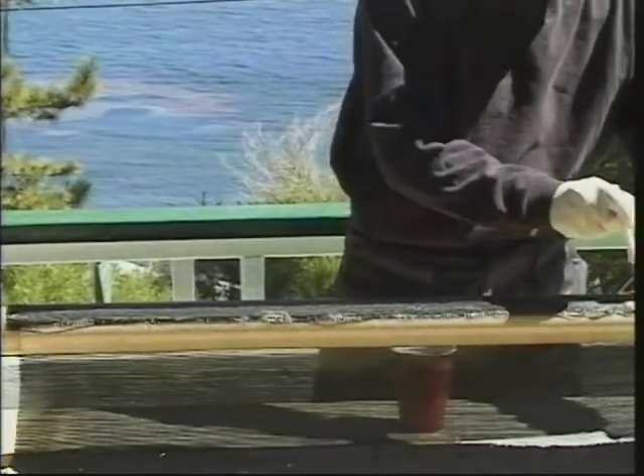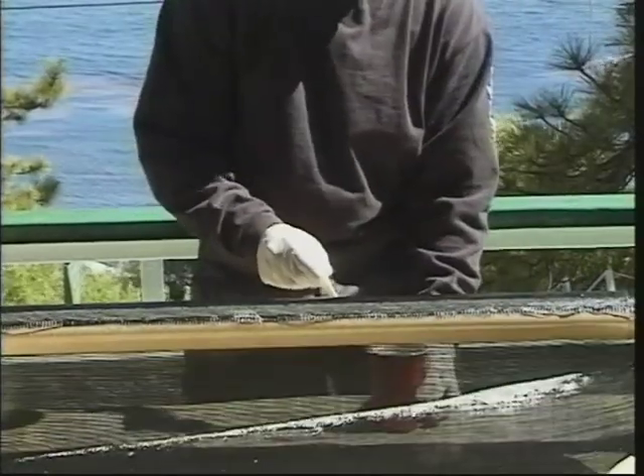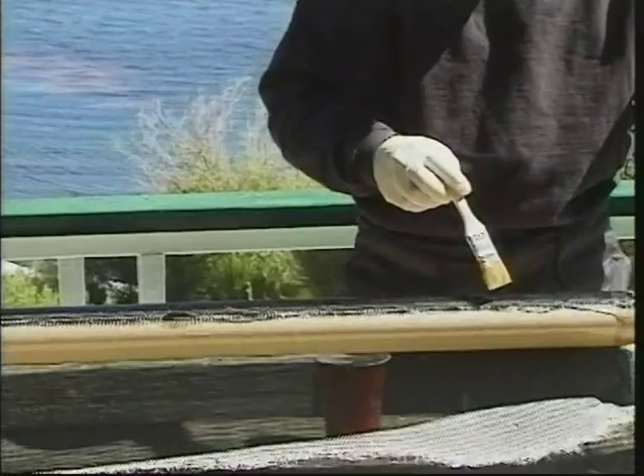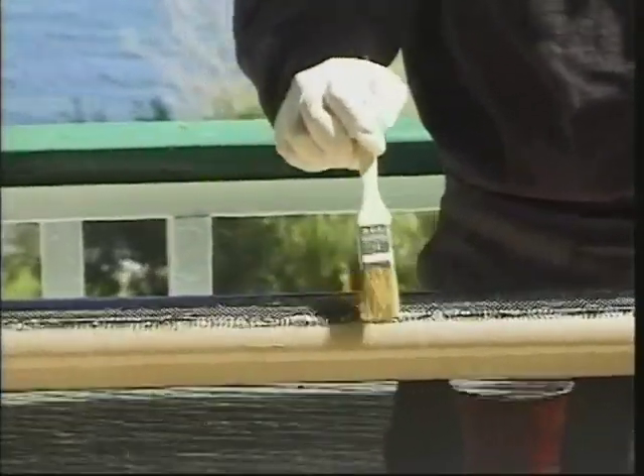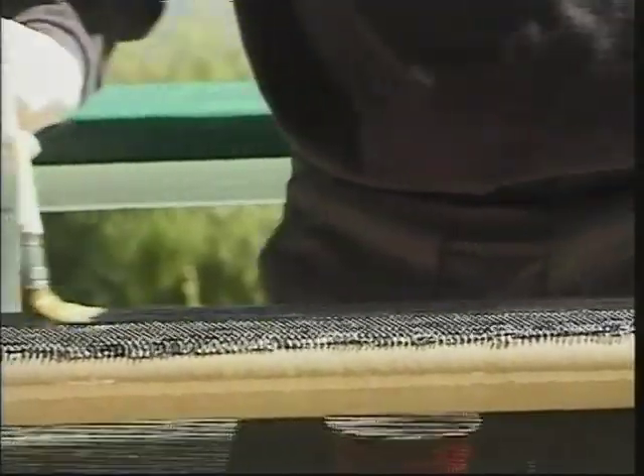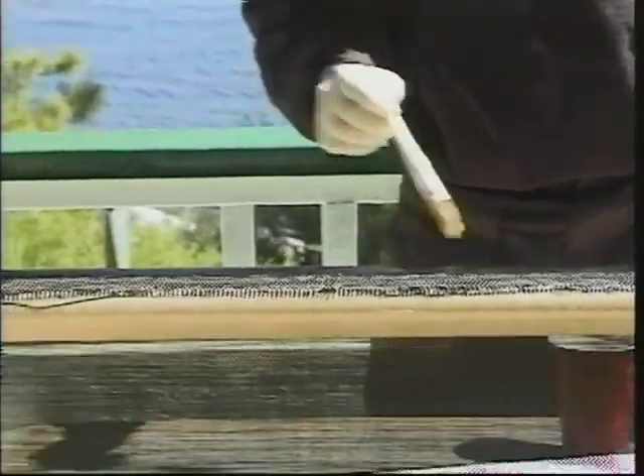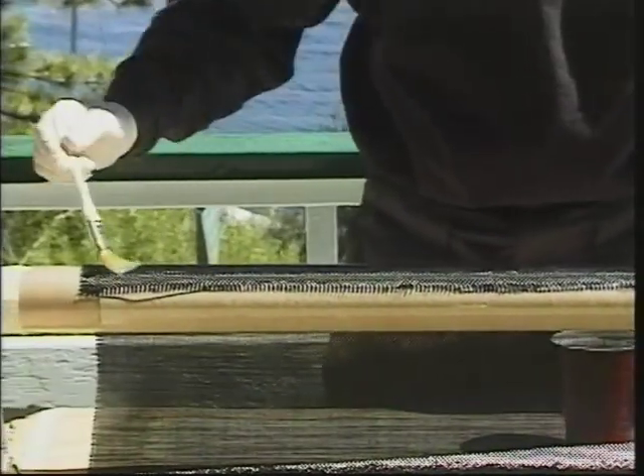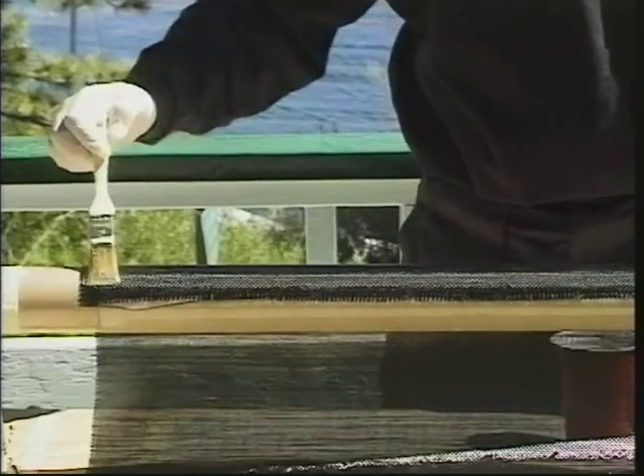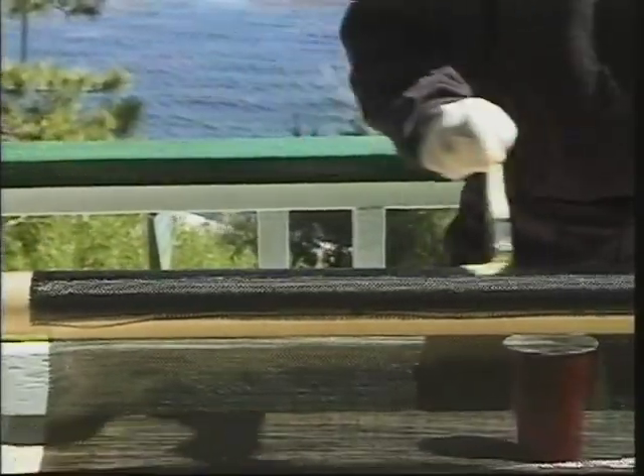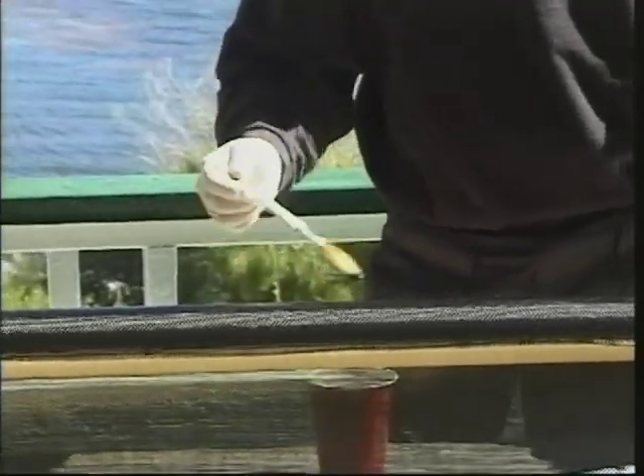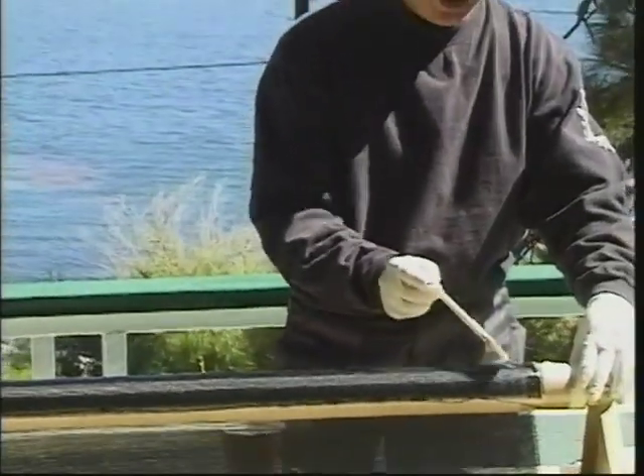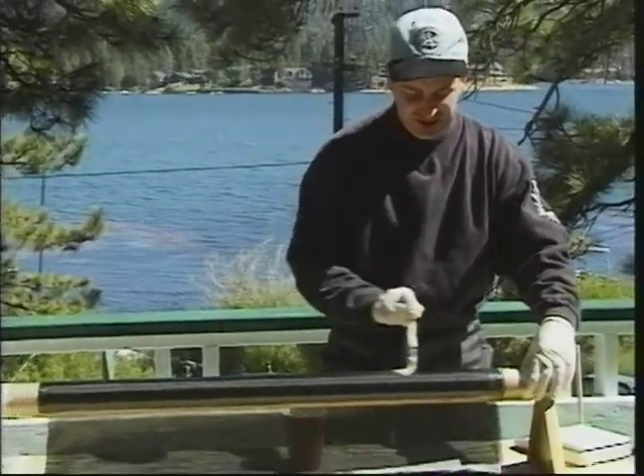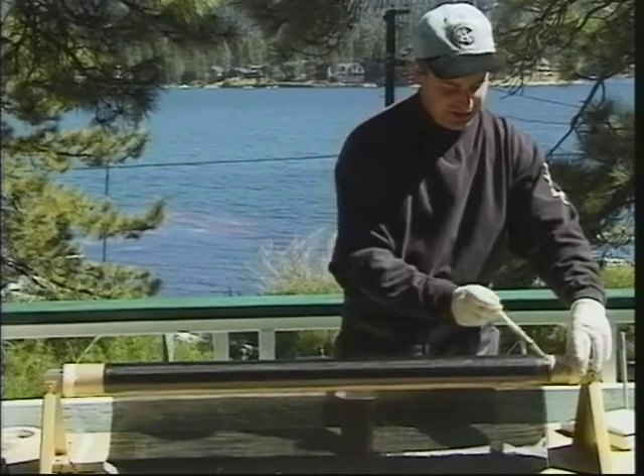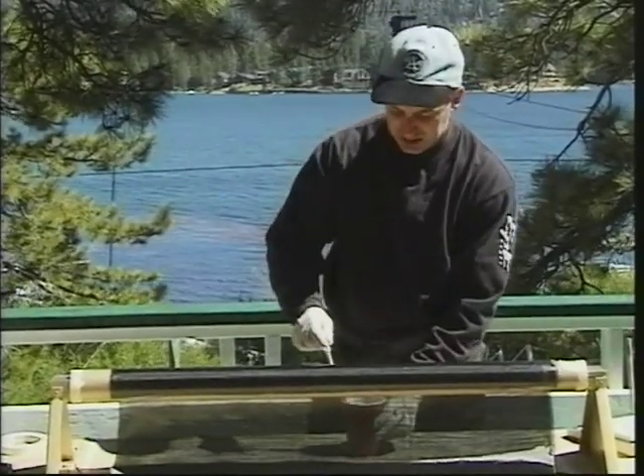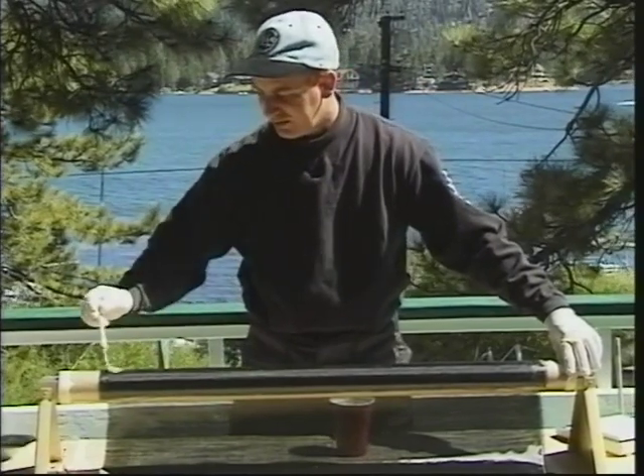I'm using a little bit more resin. It's hard to tell when you've saturated carbon fiber. You can't see it change translucency or anything like you could with the glass. So use a little bit extra, because with the heat tape winding process, we're going to be actually coming back and bleeding off that excess resin out of the laminate. Carbon is real good when you start this brushing type motion in the middle of the layup, because it doesn't move on you at all. It sticks to the tube real well, it conforms to the surface, and you can really manhandle it a little bit to get that resin on without harming the carbon.